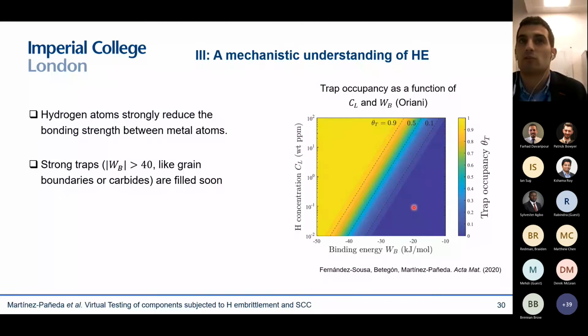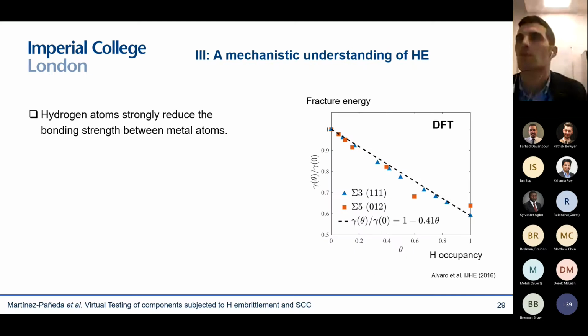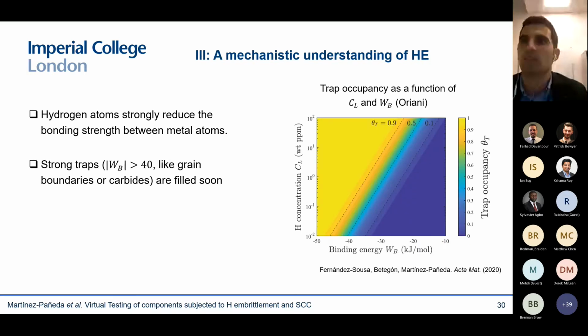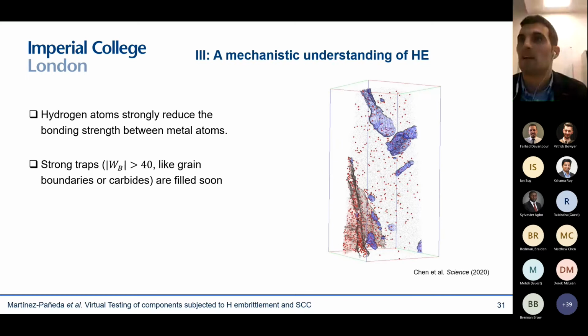And what you can see here is that for strong traps like grain boundaries, which have binding energies of -40 or smaller, very little hydrogen concentration is enough to fill the trap. You can see occupancy is above 0.95. So my grain boundaries are essentially going to be full of hydrogen. It is very energetically favorable for my grain boundaries to be full of hydrogen. And then if I go back to atomistic calculation, that tells me that I'm going to see a strong reduction in the fracture energy of this, or the strength of that grain boundary. And this is, by the way, what they see in the experiments. This is a recent Science paper from last year where they did atom probe tomography.